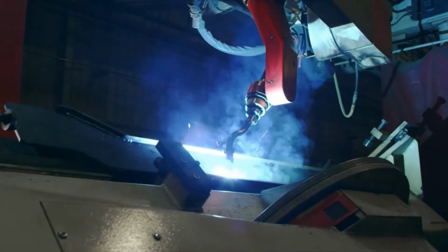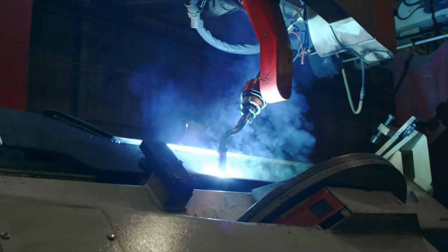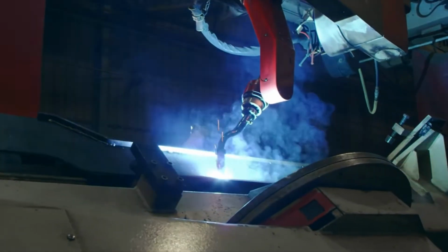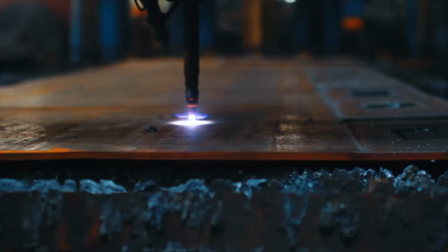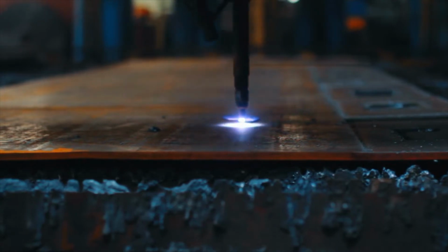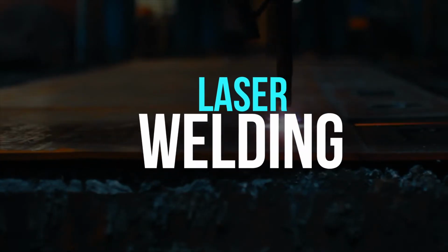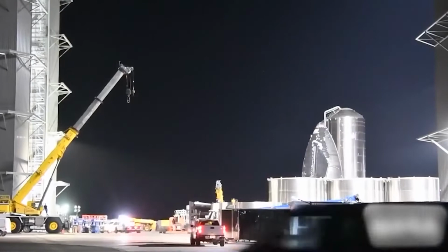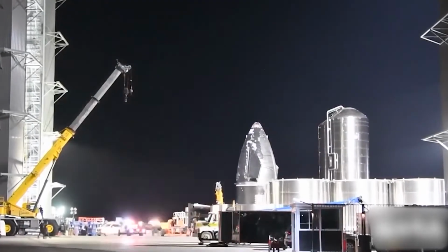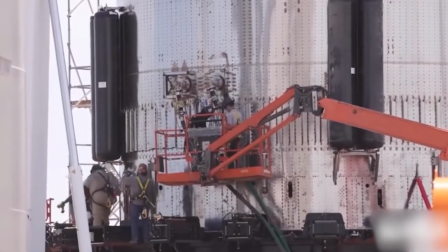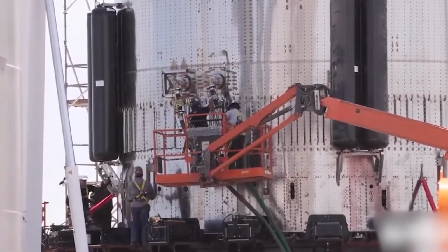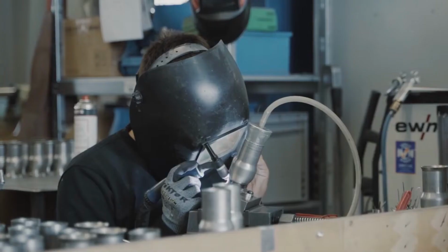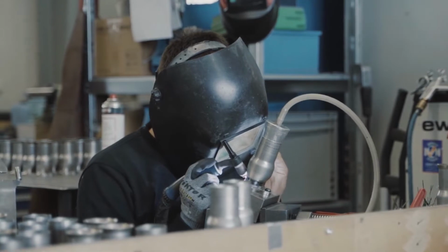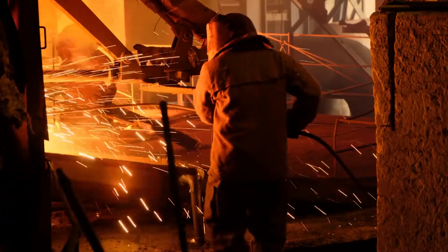Robotic welding would allow SpaceX to automate the difficult welding process and start making welds that are cleaner and more accurate. For many of the Starship sections, SpaceX has probably turned to laser welding. It is possible to weld the ring segments in a single pass because the heat produced by laser welding is more focused and penetrates the metal to a deeper depth. To increase the strength of each weld, however, a different procedure must be carried out.